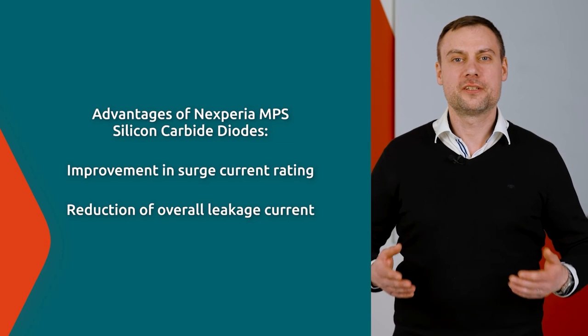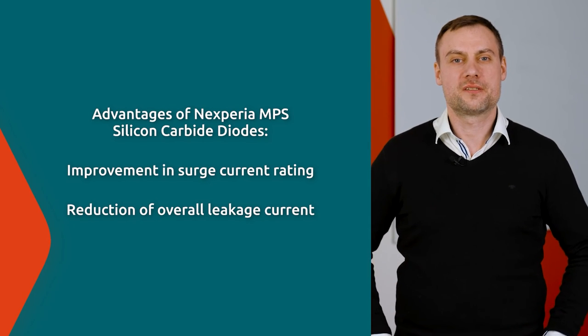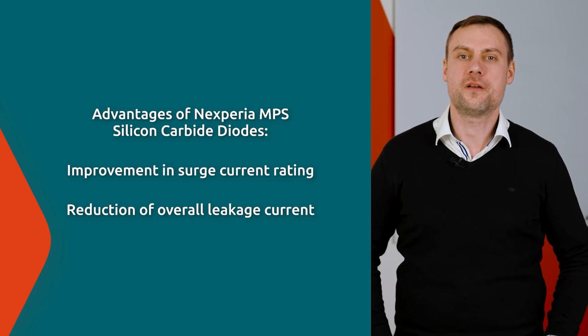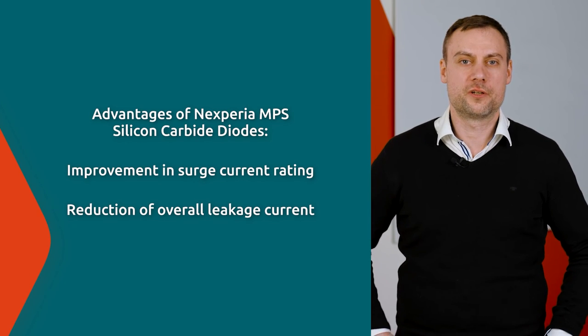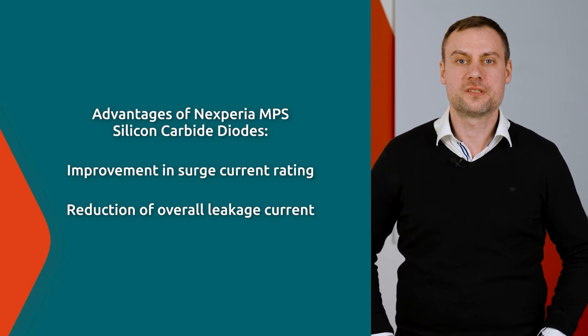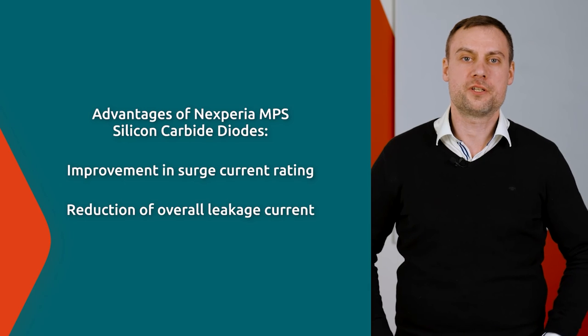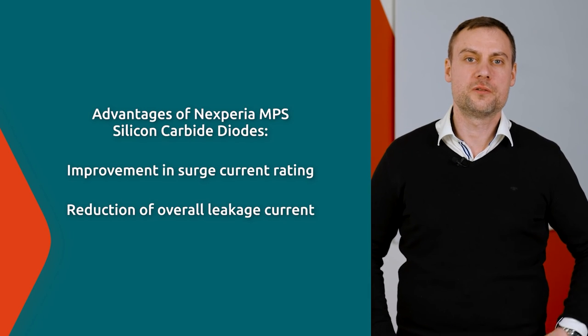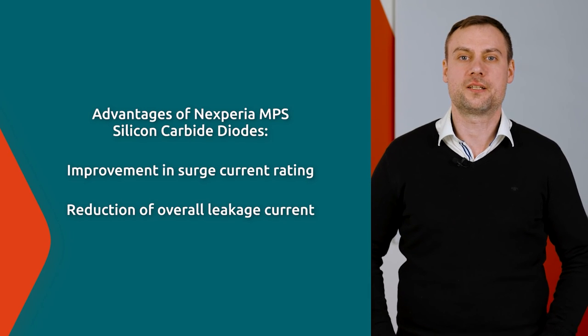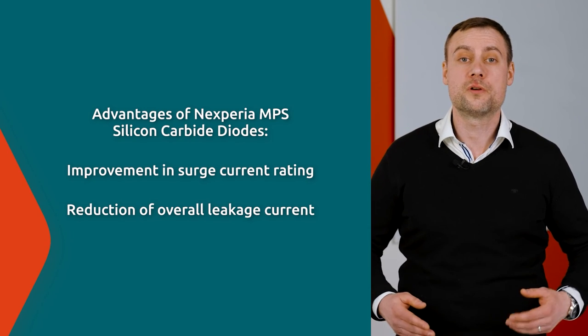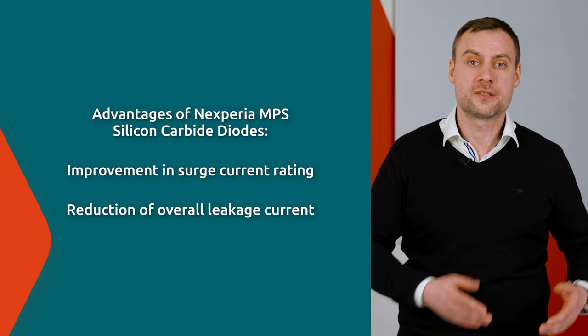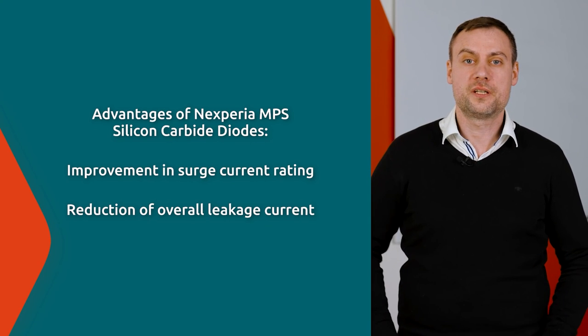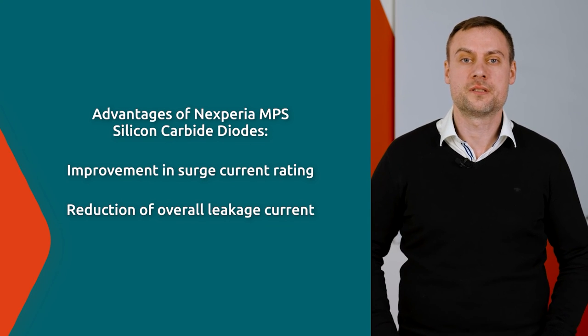In addition, a silicon carbide MPS diode offers another advantage. In the case of a transient overcurrent, as soon as a certain threshold is exceeded, the integrated PN junction activates and supports the current flow, which relieves the diode stress and significantly increases the surge current robustness.